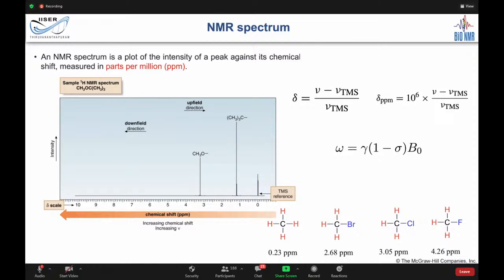Right. You should also know that omega depends on the magnetic field. So at different magnetic fields you will have different frequencies. The same sample measured at different frequencies will give you different spectra. So in order to standardize that, we have to have a reference. The normal reference we use, which is soluble in organic solvent, is tetramethylsilane, and we give the delta ppm value to be 0 for TMS.